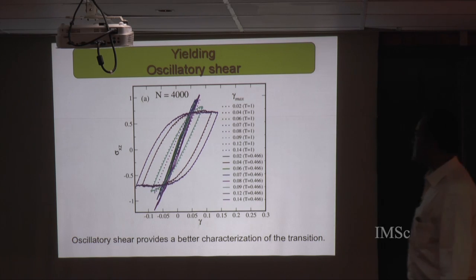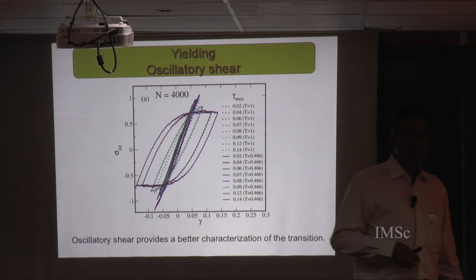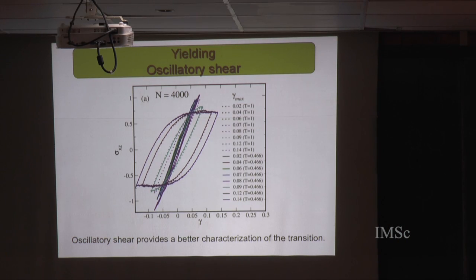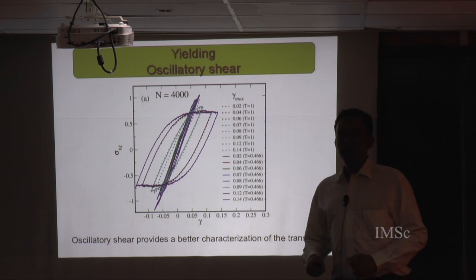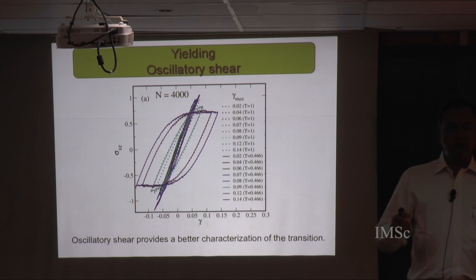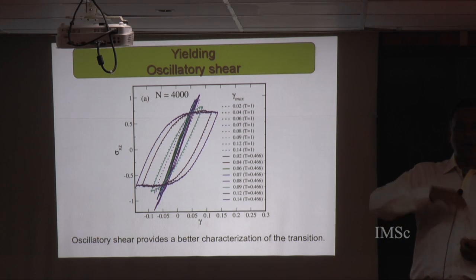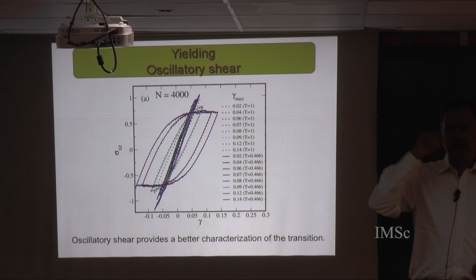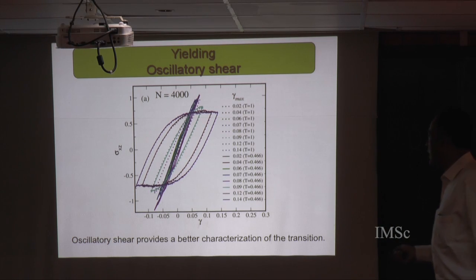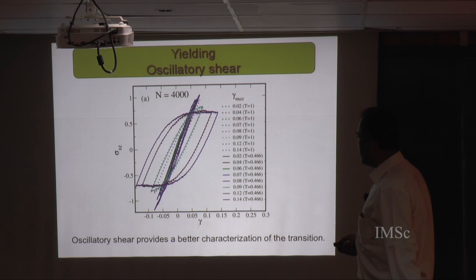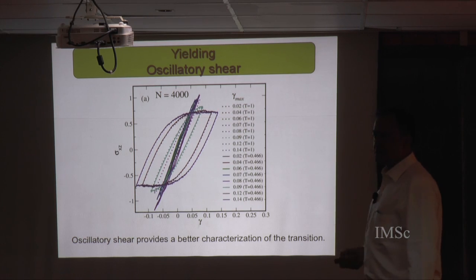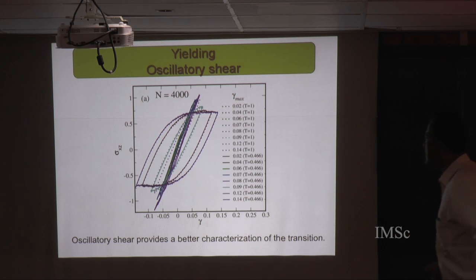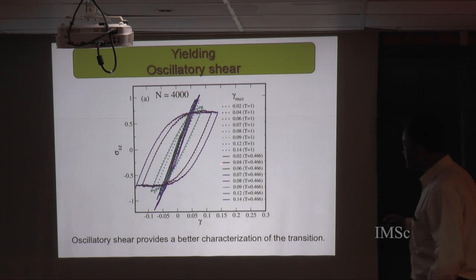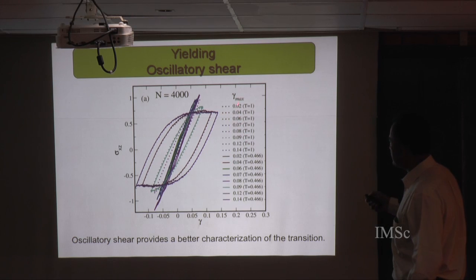So the question we ask is: can we do better by considering oscillatory deformation? When I do oscillatory deformation, at each amplitude of strain I reach a steady state with a well-defined stress-strain hysteresis loop. It doesn't have to be hysteresis, but here are the sets of all such data I generate, as a function of strain amplitude, for two different types of glasses.